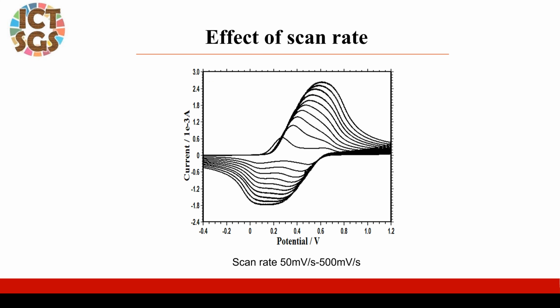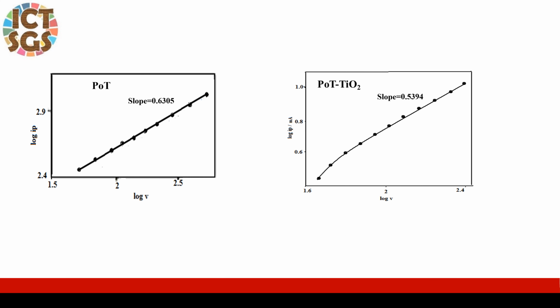The effect of scan rate ranged from 50 millivolt to 500 millivolt per second. This shows that the PoT and PoT titania nanocomposite show adsorbent behavior. From the plot of logarithmic peak current against logarithm of scan rate, these two experimental slope values are higher than the theoretical value of 0.5, which suggests that the process is adsorption controlled.